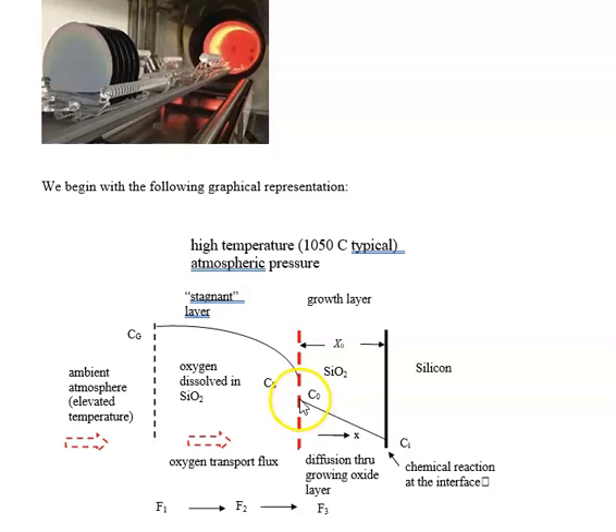And the other thing is the diffusivity, the diffusion of oxygen through the growing oxide layer. So the equation that comes out of this, pops out at the end, involves something called Henry's constant, the diffusivity, and of course the starting concentration of oxygen. So we'll have 3 main constants: Cg, H, Henry's constant, and diffusivity. And of course, driving the whole thing is temperature. So we'll have 4 actually main parameters, temperature probably being the most important of the 4.